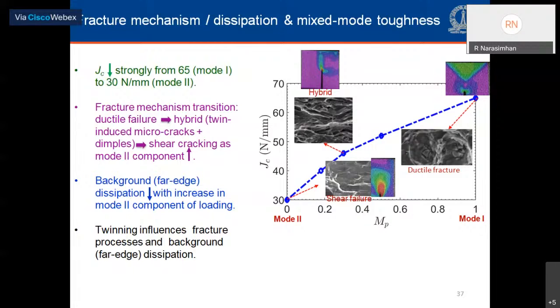Now let's try to understand the dependence of notched fracture toughness JC on the mode mixity by piecing together all this information. So I plotted the JC against MP going from the mode 1 case on the right side to mode 2, and I've also added the SEM fractographs as well as the von Mises DIC strain contours so that we can take a wholesome view of what's going on. So in the mode 1 case on the right extreme top, remember that failure happens due to ductile void growth and coalescence. Lot of dissipation caused by twinning, as you can make out from the strain contours, leading to high toughness.